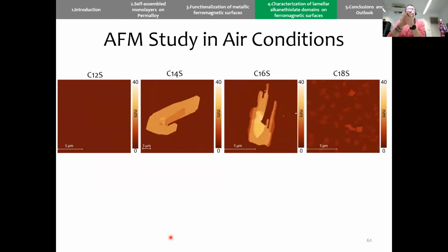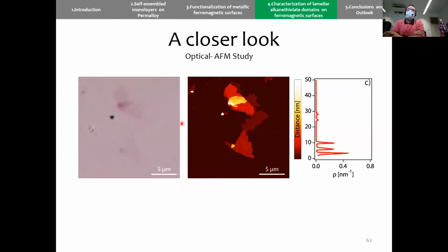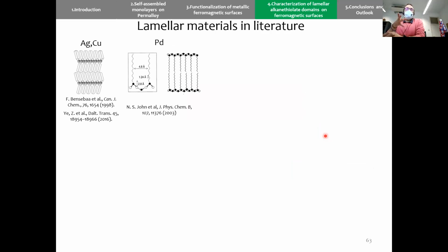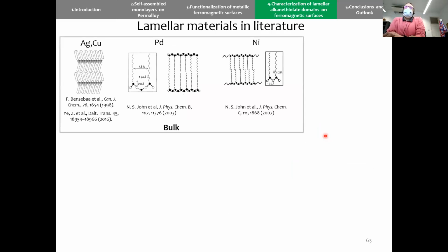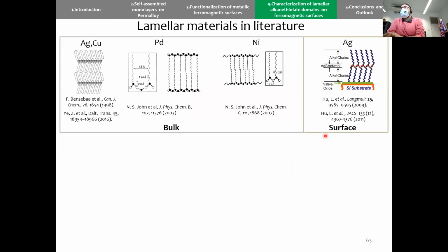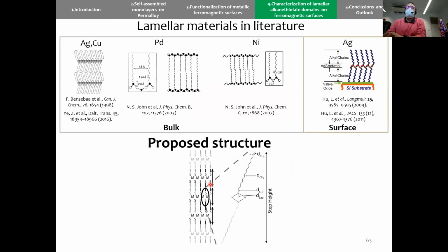Then we started studying with the AFM, and we observed that we have different thicknesses. Depending on the molecule, we can obtain different structures with also different morphologies. And we can observe this by eye with an optical microscope, and this structure presents some levels, some layers. So we went to the literature, and we observed that some lamellar materials based on transition metals were reported in the literature as bulks, or as a surface only in the case of silver. And they were proposing that they had the metal and then the broad alkyl chain, in this case coming from our SAM, extending on top and above and below the metal-sulfur plane.